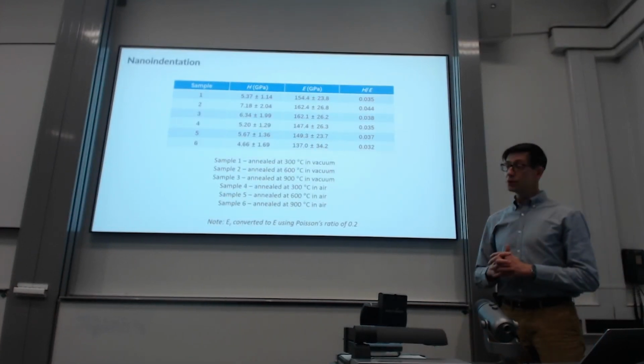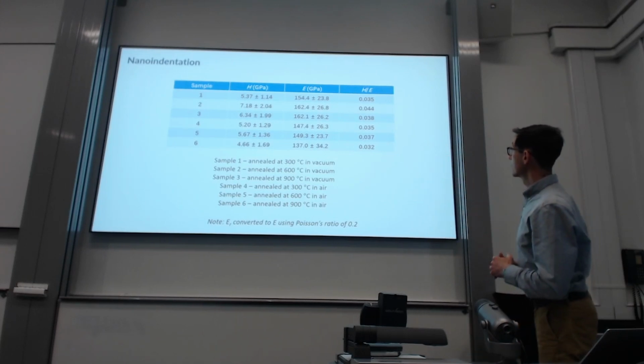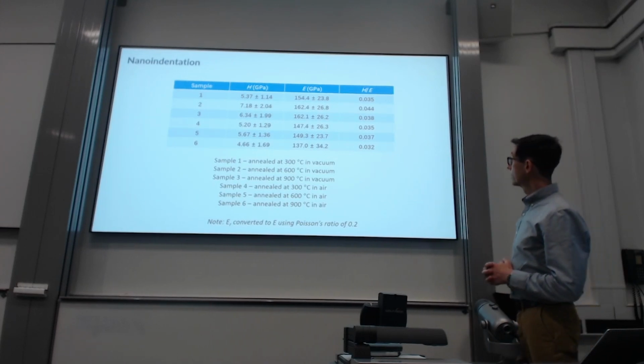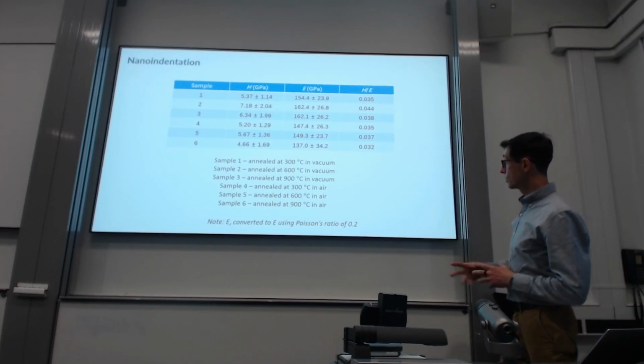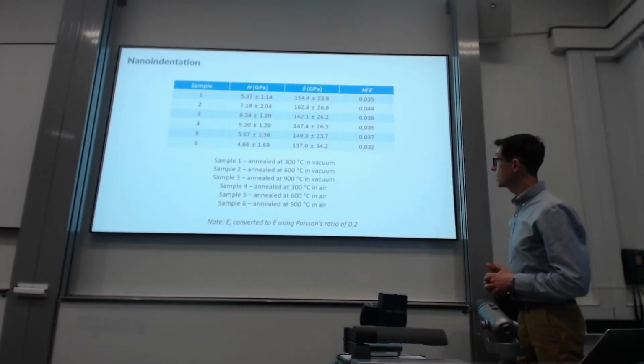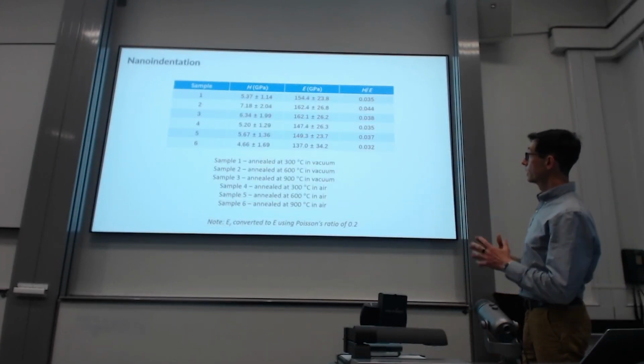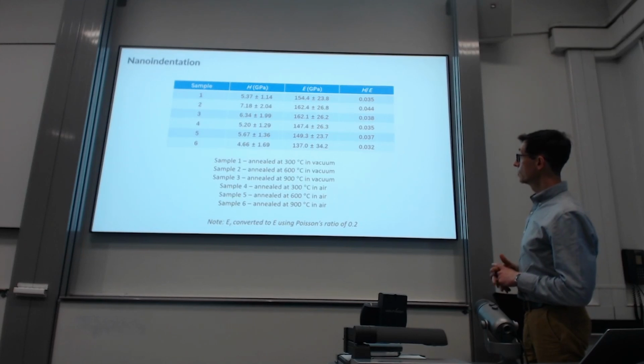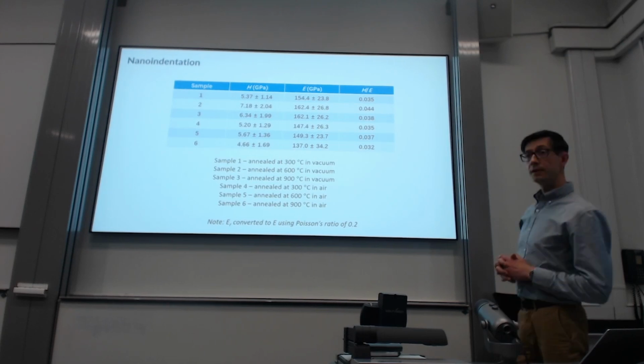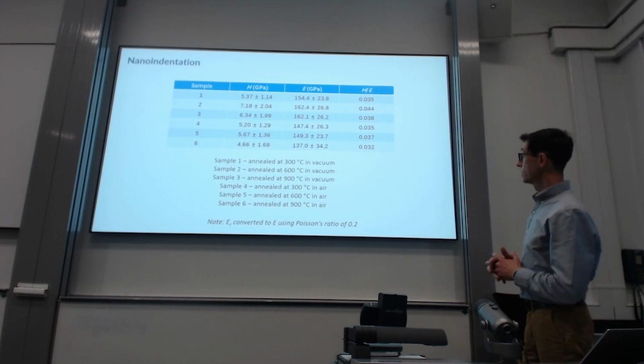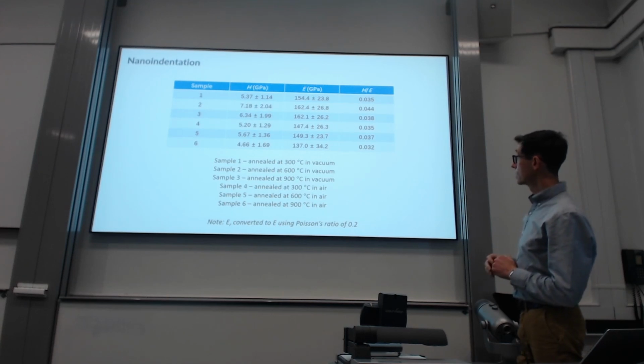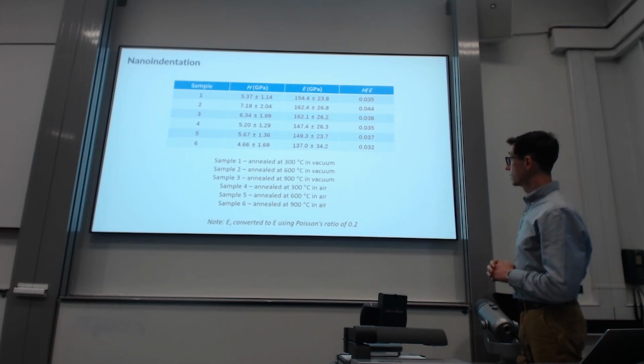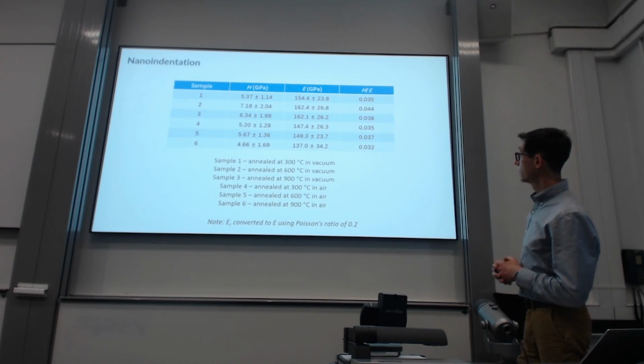So the nano indentation results: hardness, elastic modulus, H3/E2 ratio. Just as a reminder, these are our six samples. Broadly speaking, samples annealed in vacuum presented slightly higher mechanical properties, and then looking at the 3 different temperatures, perhaps 600 degrees peaks in terms of hardness and elastic modulus, both in terms of vacuum and air annealing.